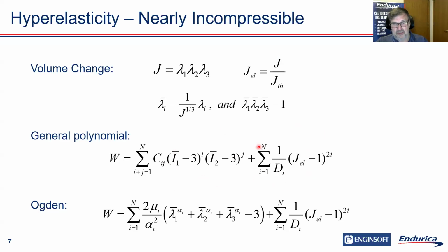The volume changing portion then is here, where we have the measure of the volume change, J elastic, and then a coefficient D, which is the material property characterizing, for a given amount of strain, how much volume change do I get? So 1 over D is like the bulk modulus. You can think about it as a material property. And in rubber, the bulk modulus is something like 1,000 times the shear modulus, which is something like the C10.